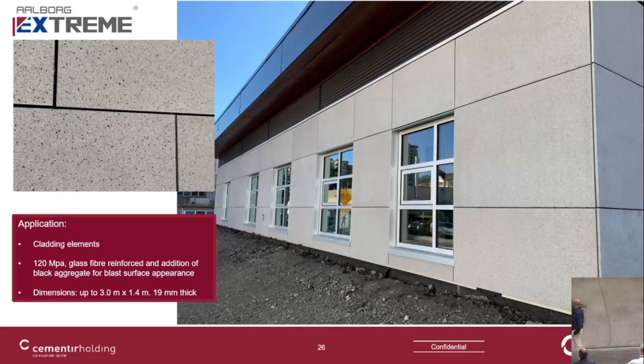And in this case, the elements are sand blasted, and they added also a small aggregate to the mix, because normally the premix is defined and is fixed, but we already did some tests also for Aalborg Extreme, for example, to add a little aggregate, and we go up to maximum 25%, and then you can also achieve this result sandblasted. You can also polish it and make a terrazzo. But the most surprising is, of course, the small thicknesses that we can achieve with this product.